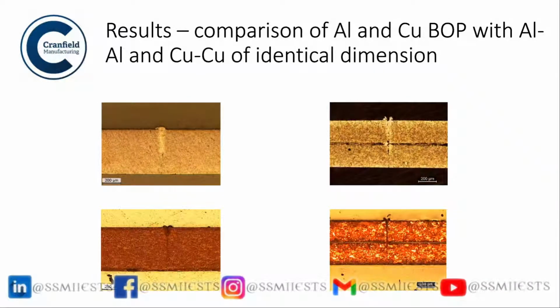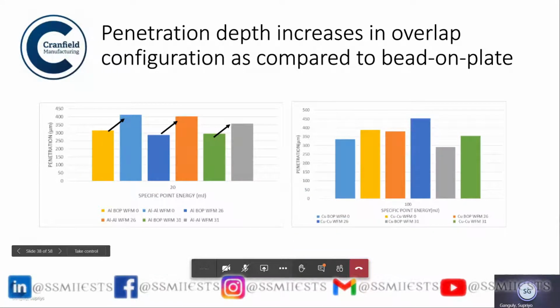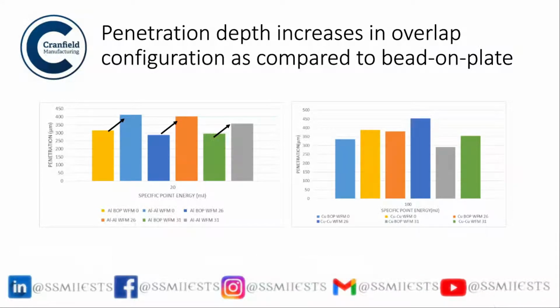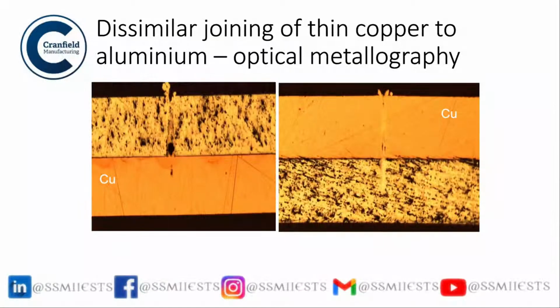So now here you can see this is 0.5 millimeter aluminium and this is 0.5 millimeter copper and this is 2.25. The interesting thing is we all thought that this one would give much higher penetration as compared to this, but that was not to be true. As you can see in the next slide, the penetration of the 2.25 millimeter parent is higher than the bead on plate of 0.5 millimeter, and the reason behind this is that the gap between the two sheets allows the keyhole to propagate faster. So this is really interesting because we always think that an integrated joint, or say when we do 2.25 millimeter, will always give you better penetration because of the heat sink that it will provide. Anyway, so these are the two configurations.